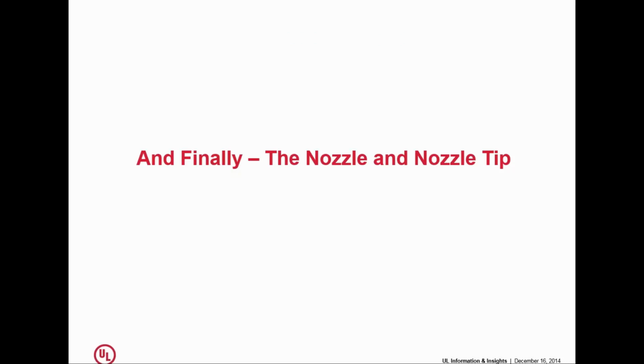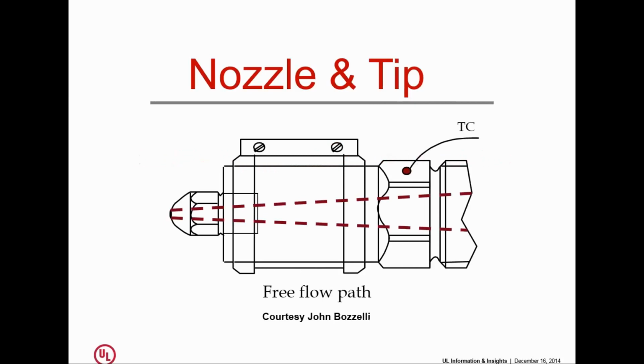Okay, and finally, I talk about picky details, the nozzle and the nozzle tip. A couple of things to consider. First of all, where the thermocouple is, because what temperature do we want to know when we talk about a nozzle tip? We want to know about the temperature right here. And so the further away the thermocouple is from the point of interest, the more likely it is that we're getting a reading that's poor. And also it's causing the heater to turn on and turn off at the wrong time.